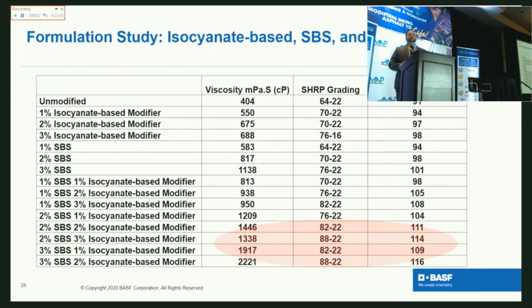Well, we can do some pretty extreme modifications with it. As you can see, this asphalt with just isocyanate did bump up that low end, but with a 3% loading, we were able to reach a 76 minus 16. It was a 76 minus 16 with an extremely low viscosity. Well, when we started using the different loadings of SBS, we got down to only a 3% SBS with a 2% isocyanate-based loading and have a 88 minus 22. At the same time, if you do it with a 2% SBS and a 3% isocyanate loading, it's also an 88 minus 22 with only a 1300 viscosity.